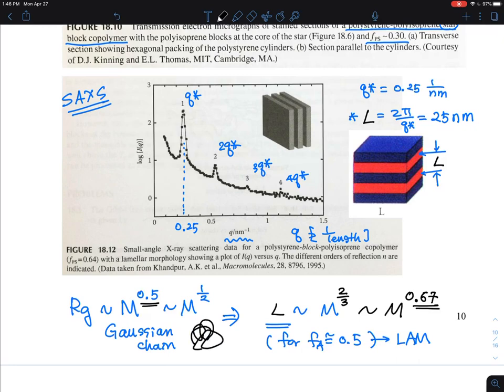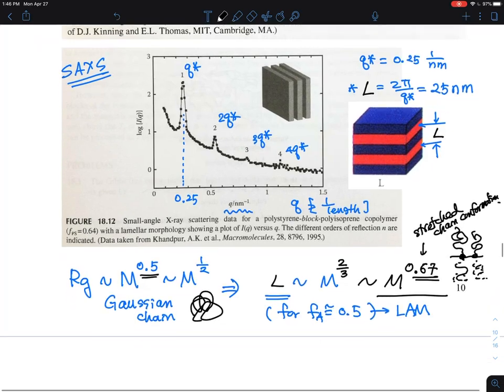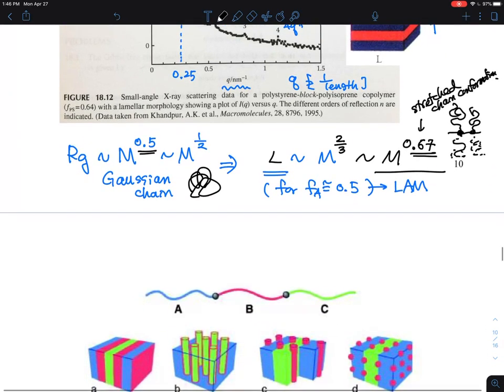This means the chain is a Gaussian chain that looks more like this, whereas here you are forcing this chain to the interfaces and they're stretched out. These are chains stretched out from the interfaces with stretched chain conformation. This has been known from experiment and verified by theory. The lamellar thickness depends a little more on molecular weight than a normal Gaussian chain, pushed a little bit further.